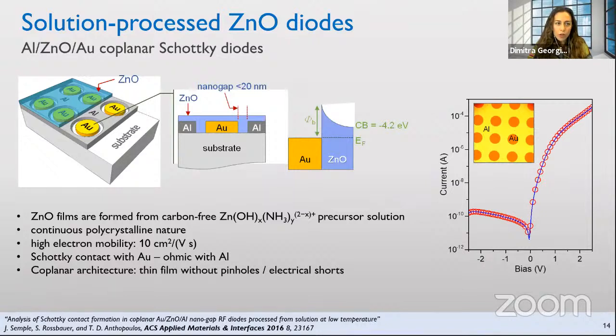So now I will show how we used those patterned substrates to fabricate our high frequency diodes. The material of choice here was zinc oxide, and we fabricated films from a carbon-free precursor solution, which gave us continuous polycrystalline films, measured in transistor configuration, having an electron mobility of about 10 square centimeter per volt second. Then by choosing the electrode configuration of our patterned nanogap electrodes being aluminum and gold, we obtained a Schottky contact with gold and an ohmic contact with aluminum.